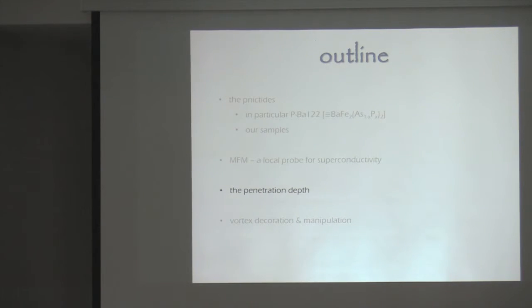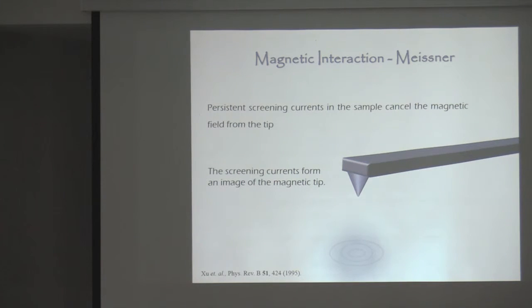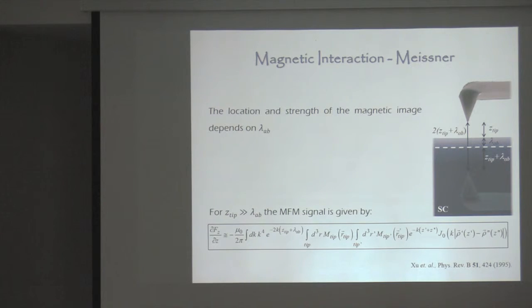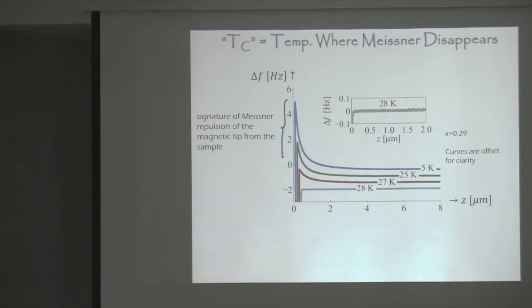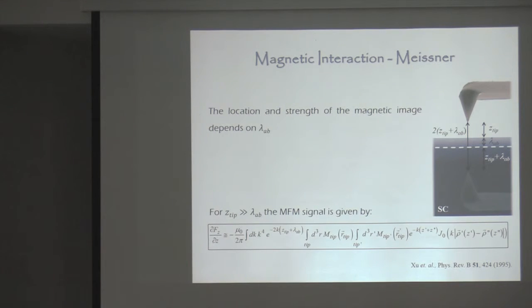Okay, so now I'll tell you how we use this to measure the penetration depth, and also how we measure the penetration depth itself. You can think of this repulsion between the tip and the sample as interaction between a tip and an image tip, really like the method of images. And then you can derive, we know the London equations, we know the Maxwell equations, you can get this formula for the repulsion of your tip from your sample, and you can see that the penetration depth appears in it. And if you have a good model for your tip, then you can use this to extract the penetration depth. Okay.